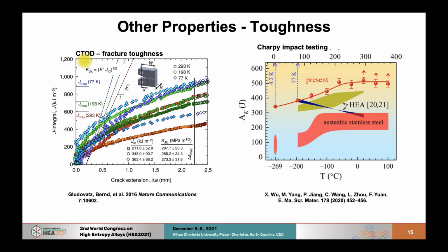And one of the first, which is really what has attracted most people, is toughness. So the Gludovatz paper I already mentioned shows this very well via fracture toughness CTOD measurements, and they show that these alloys have very large and very impressive fracture toughness that goes up when we go to cryogenic temperatures. It's interesting to see that with impact testing, with Charpy impact testing, where the strain rate is much larger,